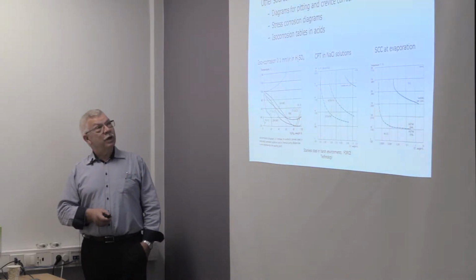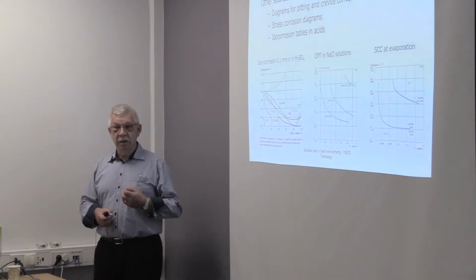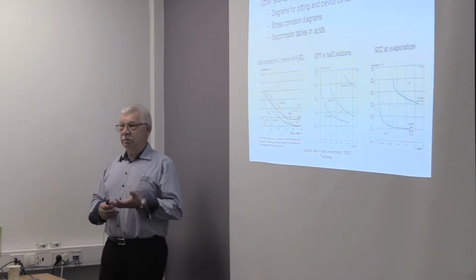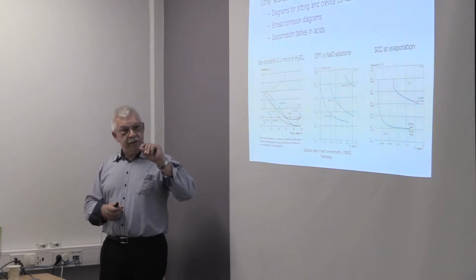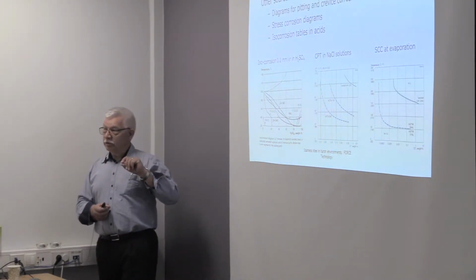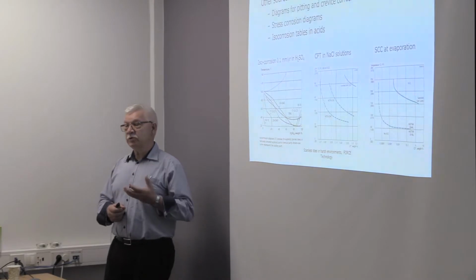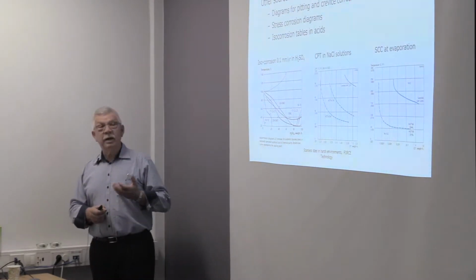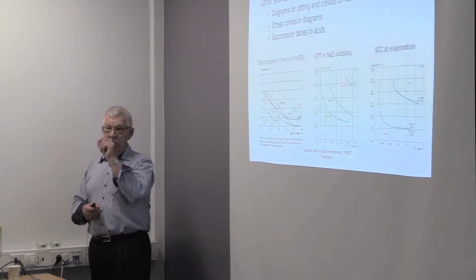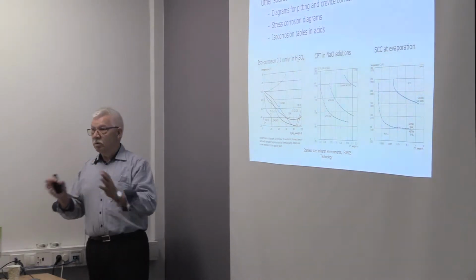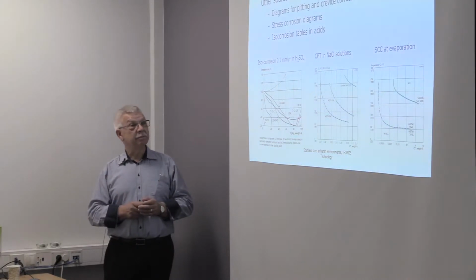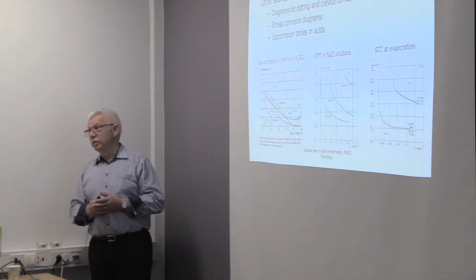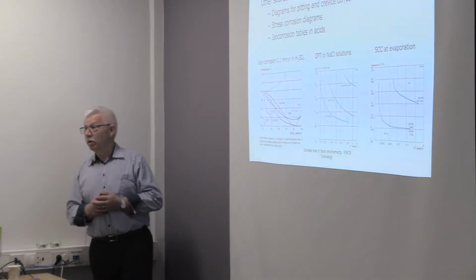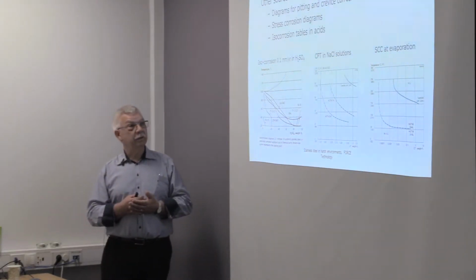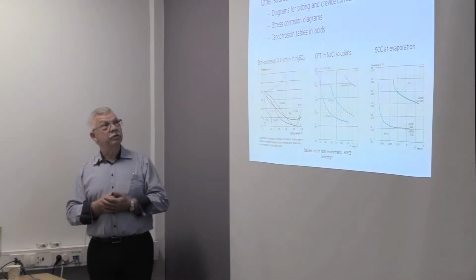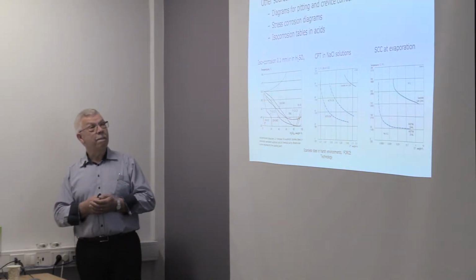Other sources: we have diagrams for pitting. When we have a material protected by a passive layer, then it will usually be localized corrosion that is the most challenging corrosion form. And local corrosion would be pitting, small holes in the surface growing to create perhaps a leak in the end. Or it would be crevices, where we have weld defects or material in a flange connection, creating a crevice where corrosion will initiate.